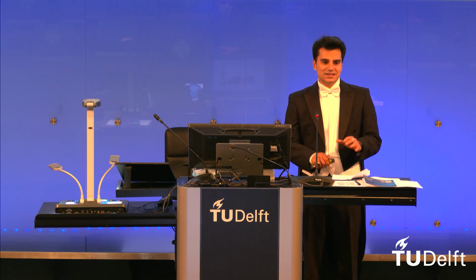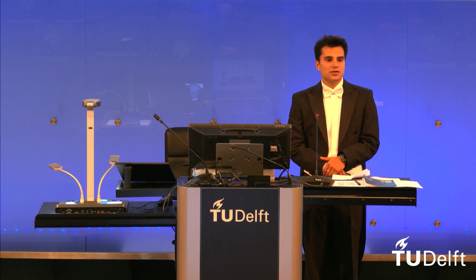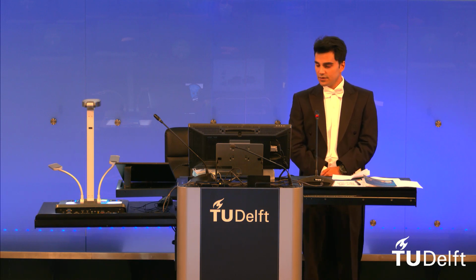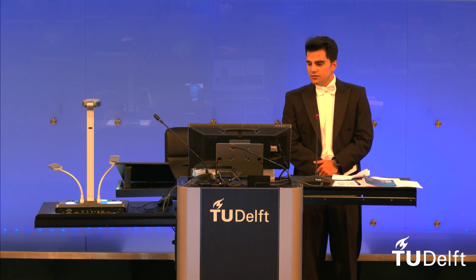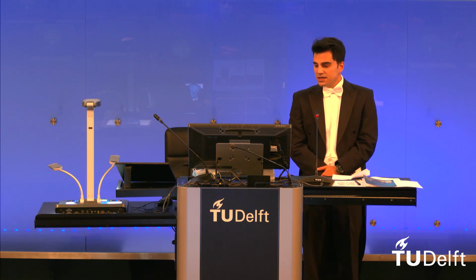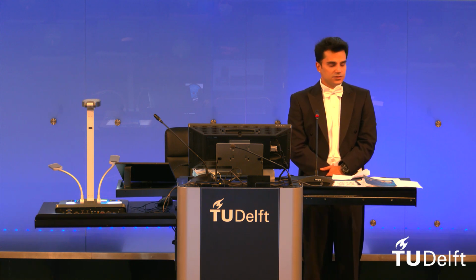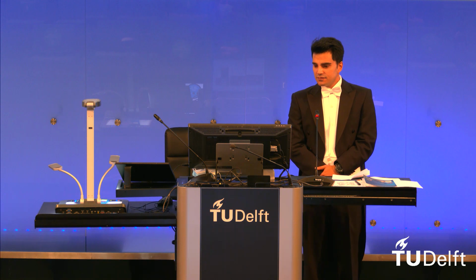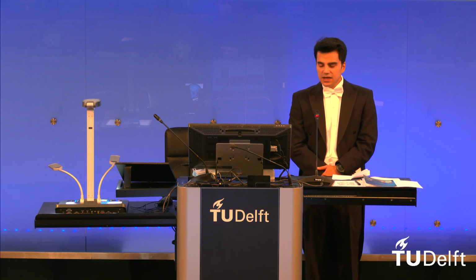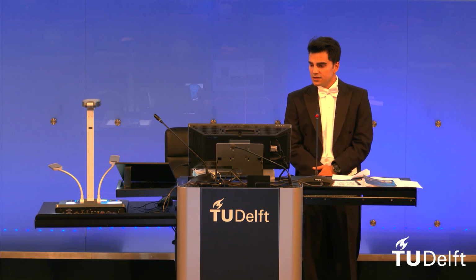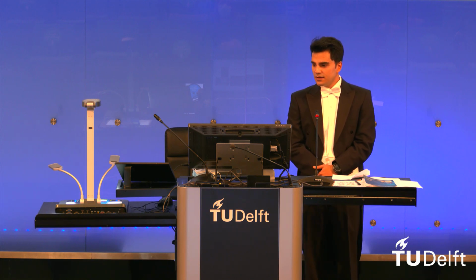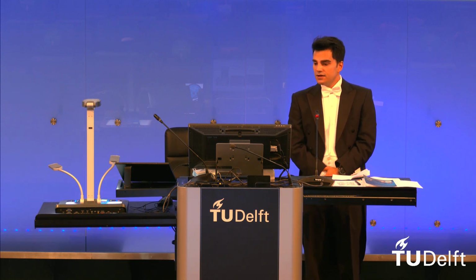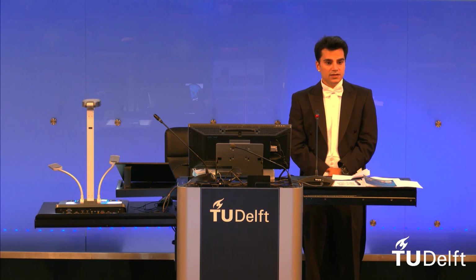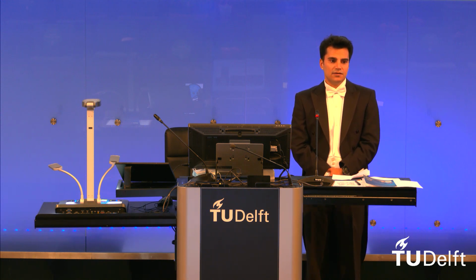And the rail circuit is relatively large in order to have less residual stresses due to the bending process of the rail. And here you see the final test rig, which is manufactured in the laboratory of the civil engineering department here in this university. As you see, that is a rotating frame structure having 4 wheel components, which will be operated on the track bed, which is a circular track bed, and it is capable of simulating wheel rail contact in a realistic situation. As you see, 4 wheels can operate in order to generate fatigue faster than in reality.